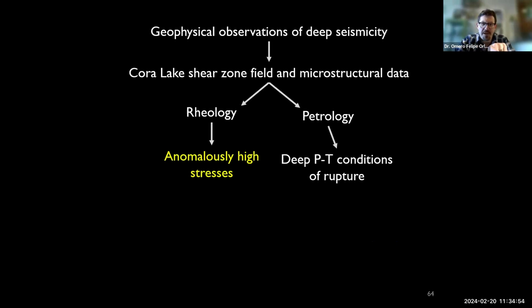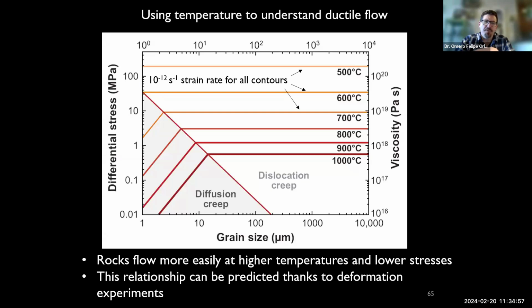And so this is an attempt to explain our anomalously high stresses. And so this plot, I probably should have taken this plot out, but this is basically summarizing how flow laws work that are experimentally determined. What it's saying is, assuming that you're in the dislocation creep regime and not diffusion creep, and I'm not going to go into the difference between the two because we're mostly dislocation creep in this project, as you increase temperature, which is these bars going down, the viscosity goes down at a certain strain rate. This is really a mathy and complicated way of saying that as temperature increases, rocks get easier and easier to squish. They flow more readily at different strain rates.